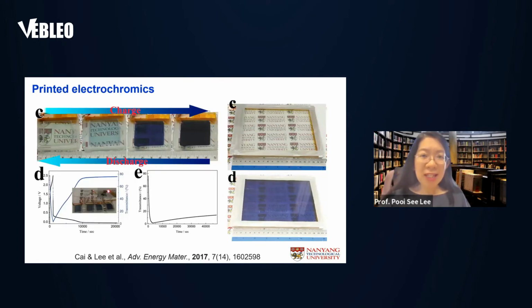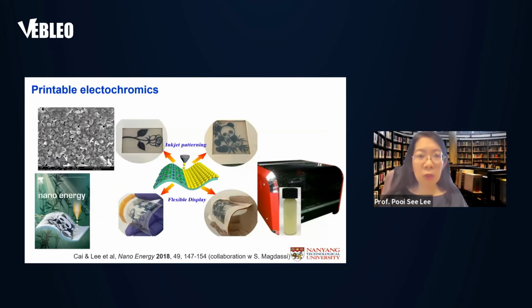So on the printing aspect, improvement on the printable ink as the electrochromic active layer is very crucial. Here, we formulated the tungsten oxide nanoparticles that are homogeneous with structural sizes of less than 100 nanometer and able to be coated using inkjet printing over large area, as can be seen here in figure D. It is a substrate of more than 20 by 20 centimeter, and the performance is relatively good.